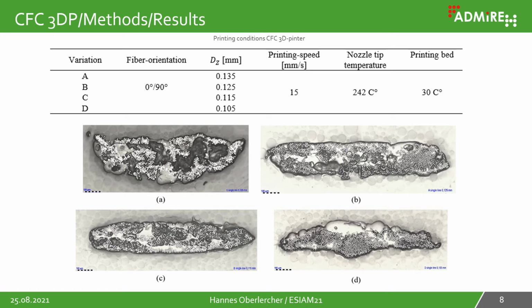In the pictures below, you see one line; we printed one line in X direction and made a microscopy image and analyzed the microstructure. You see at sample A a very high content of cavities inside, and also the fibers are not well distributed in the matrix. Samples C and B have a much lower content of cavities and the fibers are better distributed inside, and sample D shows the best results, a pretty low content of cavities inside, but the fibers are not well distributed in the matrix material.